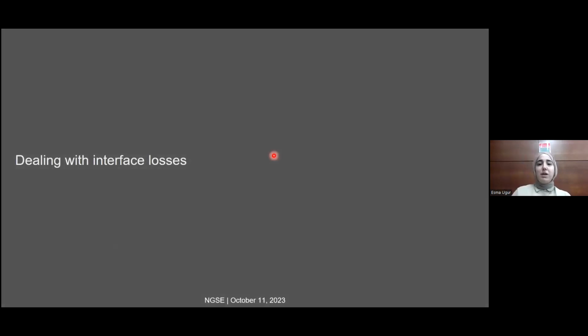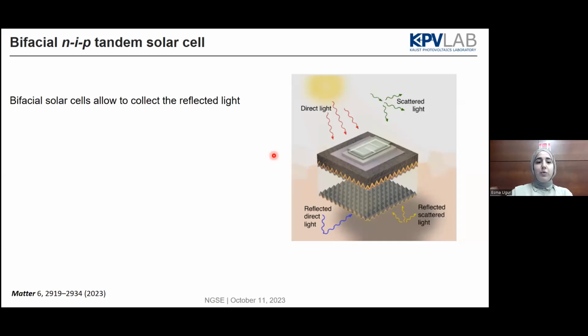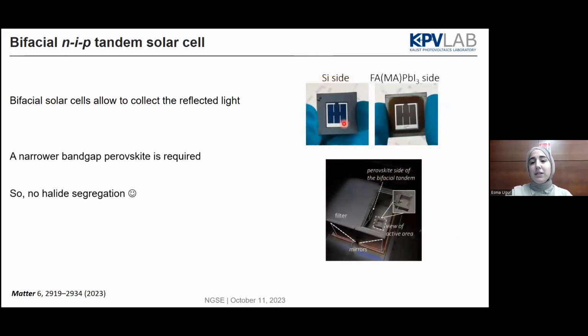Now I will give you some examples while we are dealing with these interface losses. First of all, I want to show you how we are dealing with the losses for the NIP tandem solar cells, but this time it will be the bifacial device. So the bifacial device is actually not only getting the direct light from the sun, but also the scattered or the reflected light from the backside of the device. That's basically that you don't have an opaque device at the back, but you have a transparent one. This is the backside of the device, and this is the front. So we have the same active areas for both sides so that you can collect the reflected light from the back.